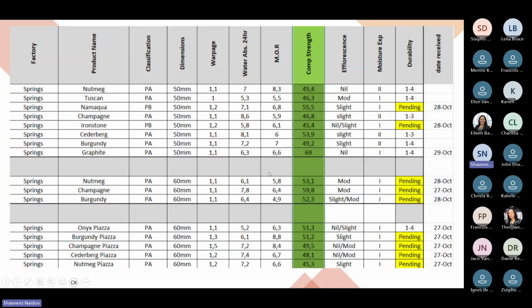And I don't know if I have a pointer here. Yes. So basically, if you just look at the nutmeg paver, and the modulus of rupture, they show 8.3, but the actual compressive strength is 45.4 MPa. So a lot of engineers, we like to explain to them that you must compare apples with apples. And if you are comparing modulus of rupture, or if you want to, then you can compare the compressive strength. So we've just made this document available so that they can compare actual compressive strength with compressive strength, or modulus of rupture with modulus of rupture. And you'll see our pavers are ridiculously engineered. The MPa compressive strength is ranging from 45.4 to 69 MPa, which is very, very good.